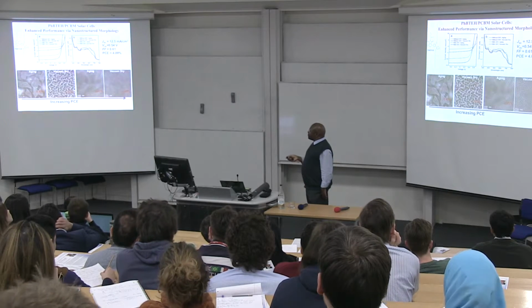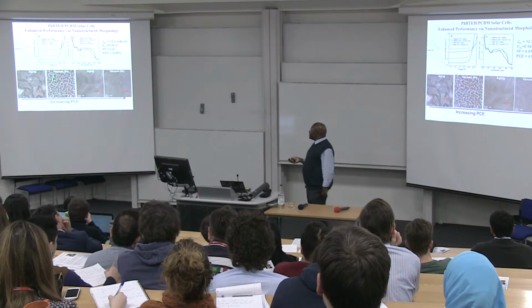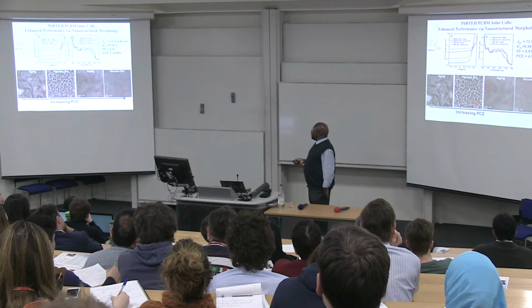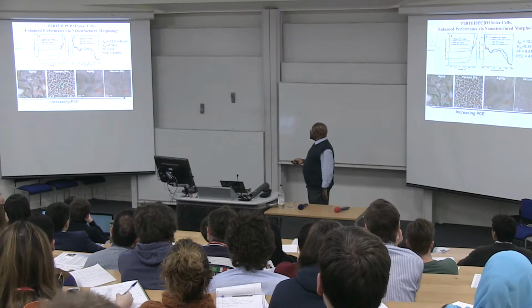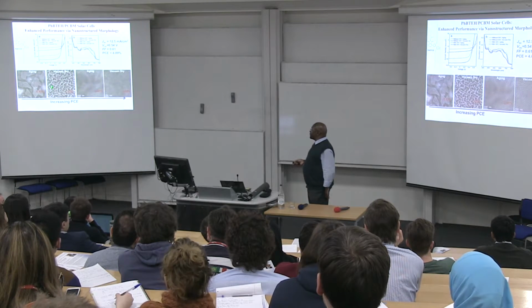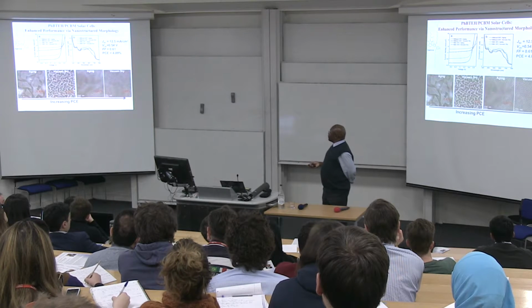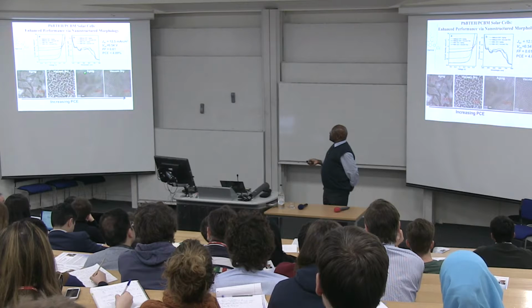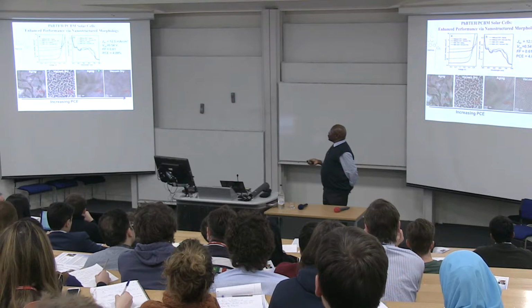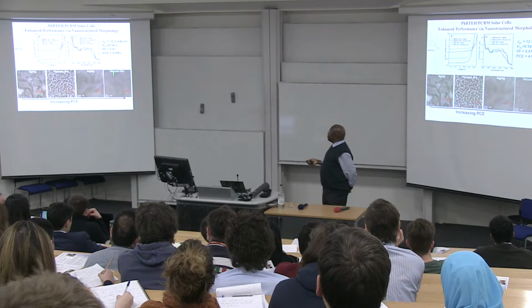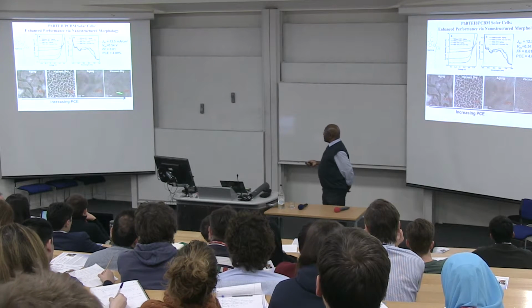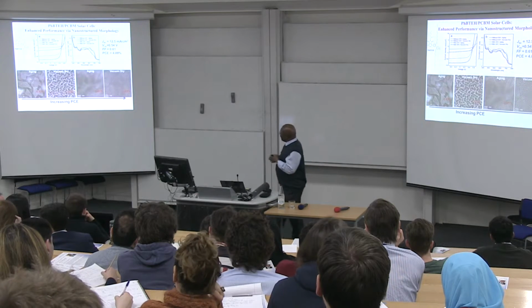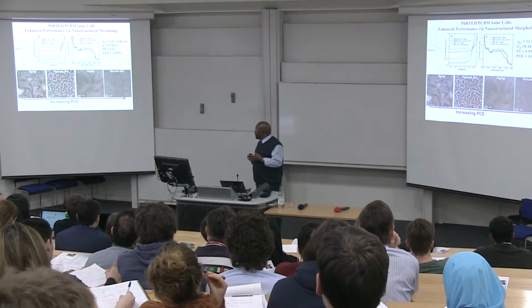On the other hand, by adding some additive to the process, and then, here, just taking the same film and drying it very fast in vacuum, you can improve the efficiency. On the other hand, if you add additive and you dry in vacuum very fast, as you can see, you structure it more so that the domain sizes are more in the nanoscale, and that improves efficiency of devices.